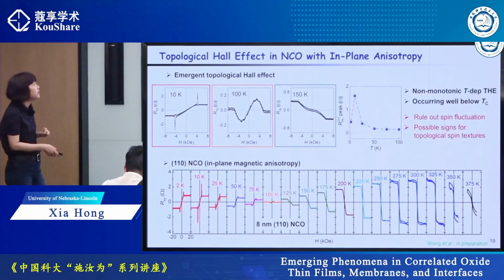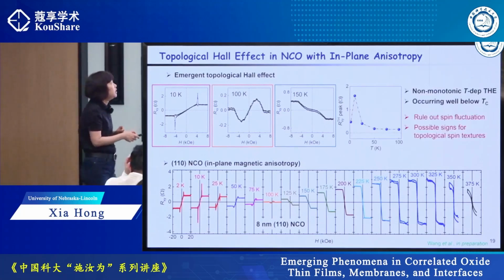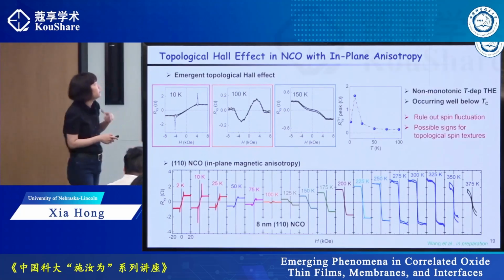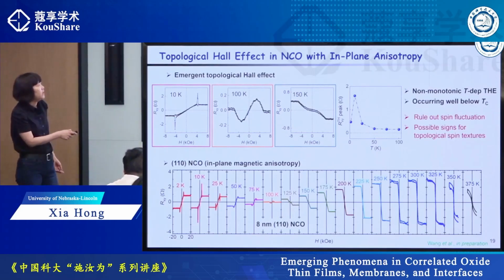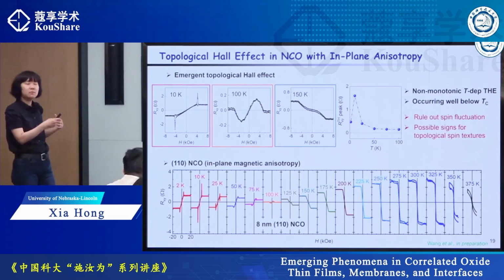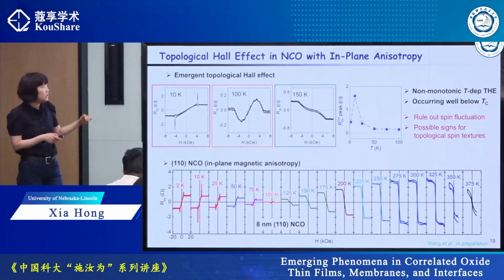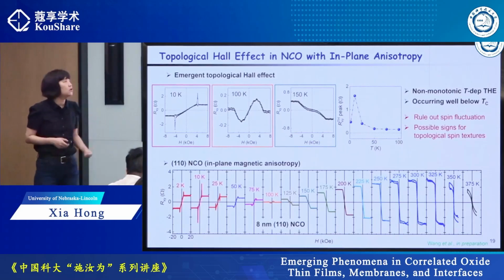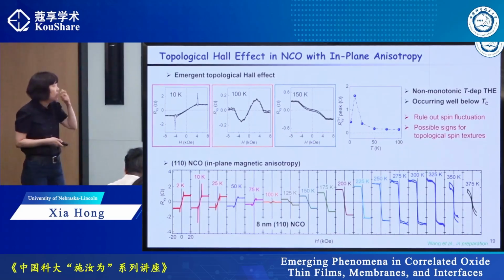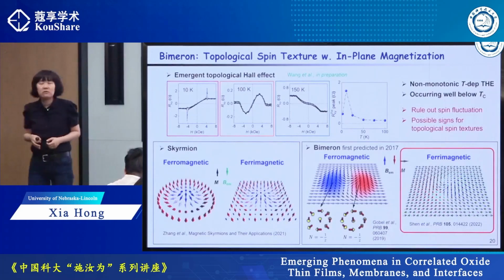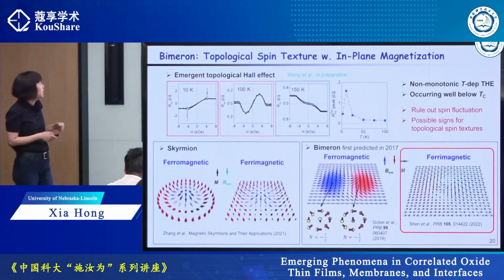And we extracted the topological Hall amplitude and find it peaks around, I think, 10K, and that is far from the Curie temperature, so we can rule out spin fluctuation as the origin of this topological Hall effect. And it's a possible sign that we indeed have a topological spin texture. The question is, what is the origin of this topological spin texture?